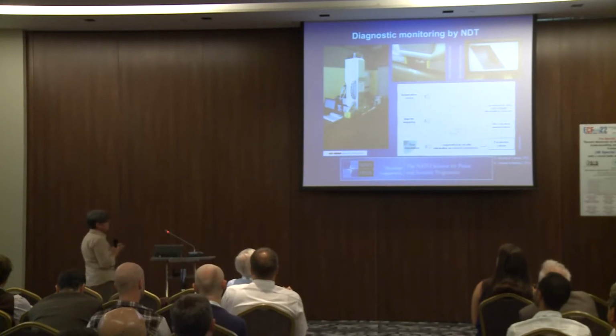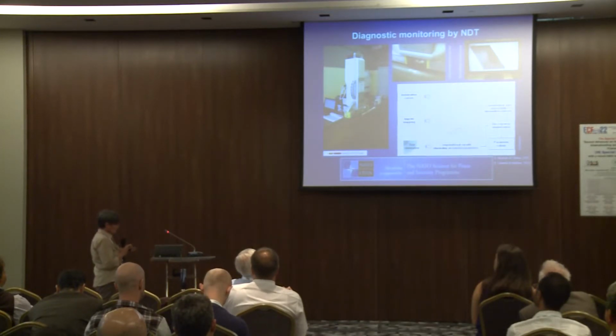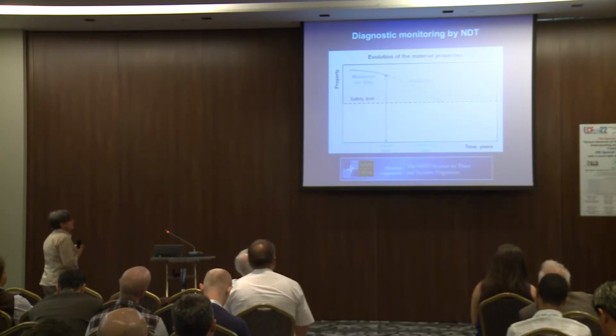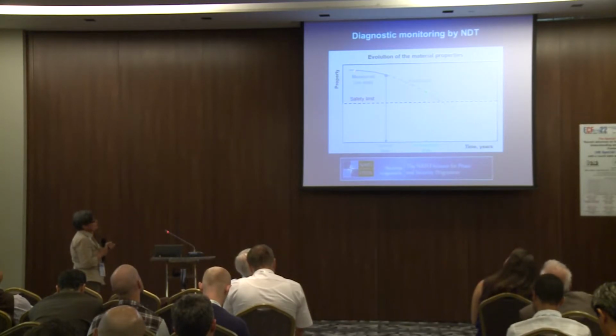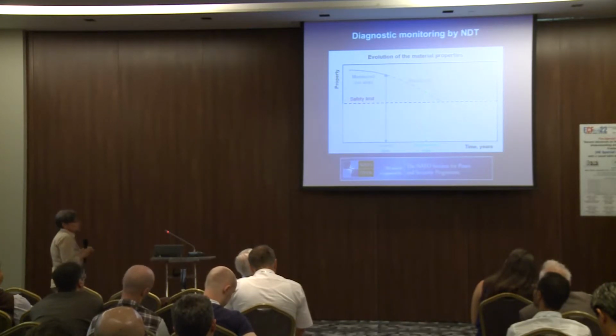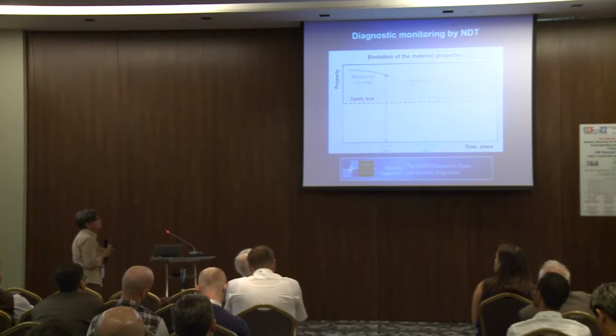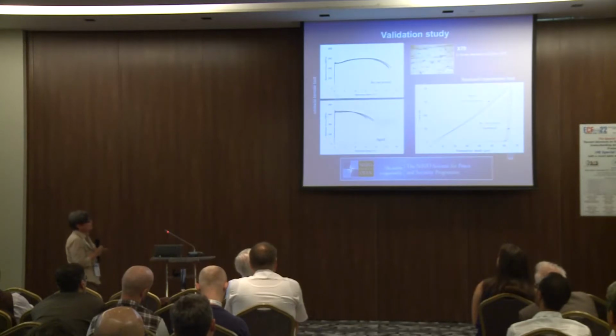So the former study concerns the standard steel, and the typical loading level was 2 kilonewton maximum load. This is a very fast approach, and the idea is to use this kind of monitoring tool to take measurements from time to time, and then to infer the evolution of the material properties in time, to be able to design the right intervention times for structural retrofitting without having to pay too much, but at the same time avoiding possible disasters.